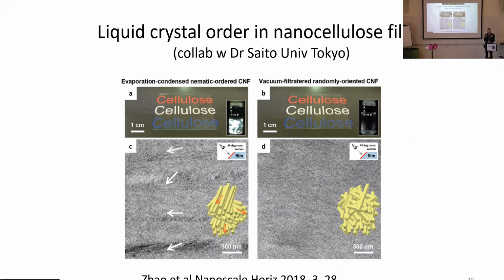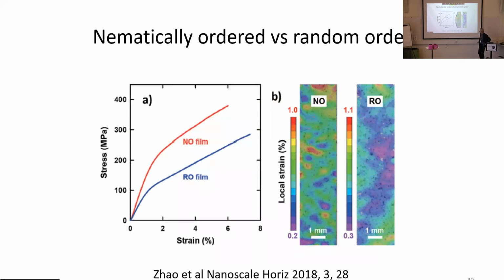This normally only happens when you have rod-like cellulose nanocrystals, but these are fibrils, and they still show this liquid crystalline order. So in one case, when you do it slowly, you end up with some liquid crystalline organization. If you do it rapidly by filtration, you have a more random organization. Does it matter? Yes, it makes a big difference. And these are mechanical properties for these films. This is the random film, stress versus strain, the randomly organized film, the nematically ordered. And you see there is a substantial difference in mechanical properties.